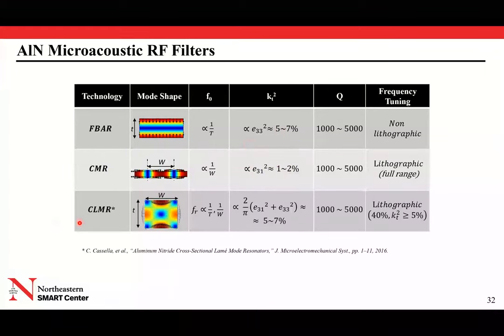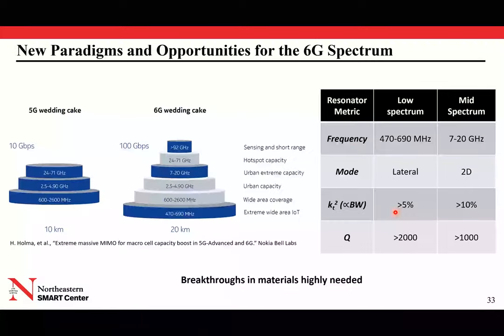So we developed this cross-sectional Lamé mode resonator technology that basically combines the advantages of these two technologies. Basically we assign a Lamé mode, which is a mode of vibration that's a two-dimensional mode displacement vector in the cross-section of an aluminum nitride piezoelectric thin film. So this uses the piezoelectric coupling coefficients, so we achieve coupling coefficients comparable with FBAR, but also has some lithographic tuning capability, which is very important, especially scaling at high frequencies.